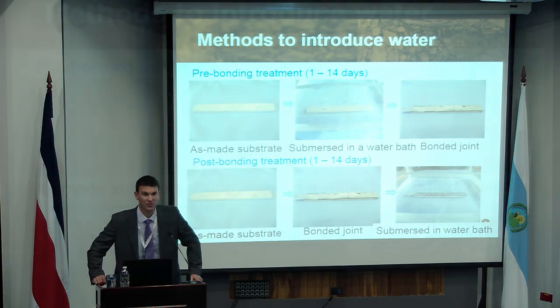The idea is that you have allowed water to enter that aggregate, and once you've surface dried the top of that aggregate substrate to allow you to prepare your specimen, you will have access in terms of water that is still inside the aggregate to diffuse to the interface. And we can look at the results in a second to show how successful that particular approach was. So that's the pre-bonding moisture conditioning protocol that we developed.